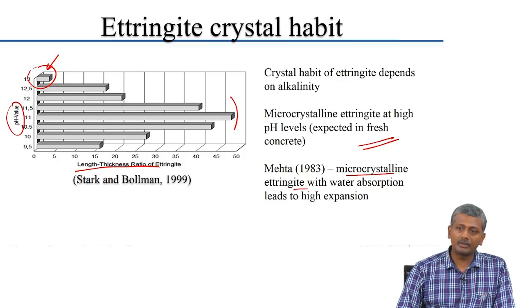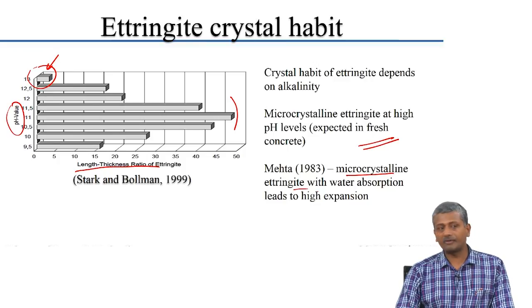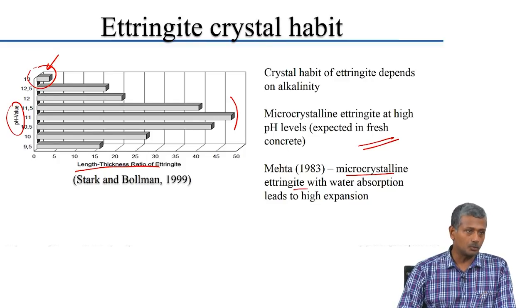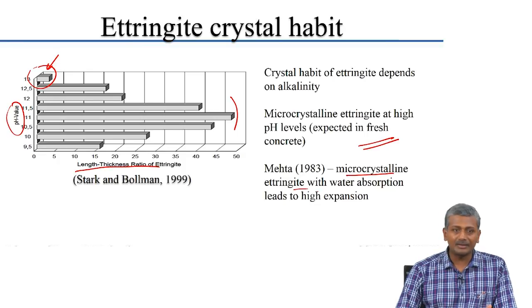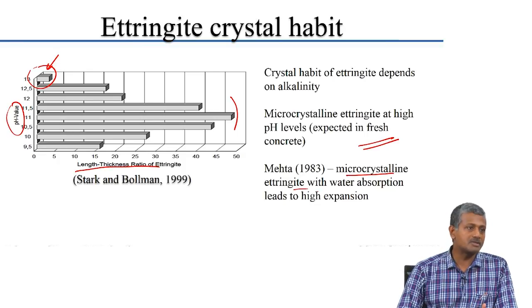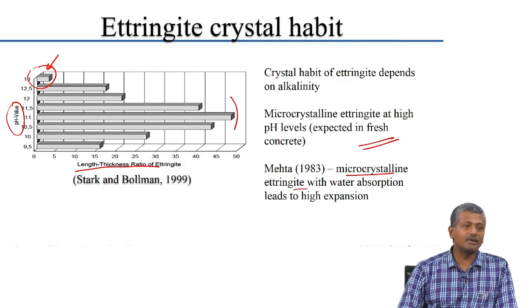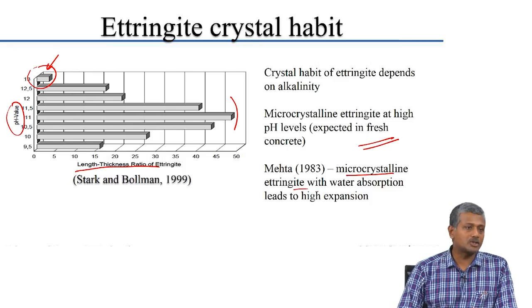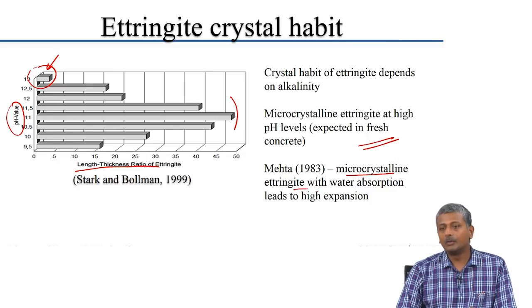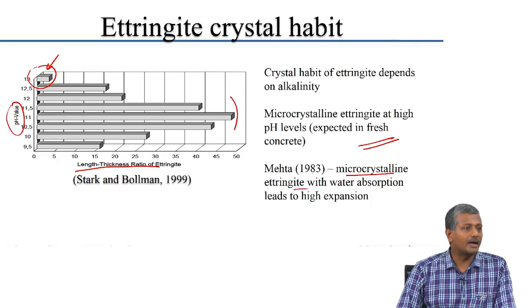When sulphate exposures bring down the pH — for example when you have lower pH levels in the surrounding environment — the ettringite that actually forms in the system may not be highly absorptive. When this ettringite does not absorb or imbibe water, it does not lead to very high expansions. So ettringite formation can lead to expansion primarily only in those conditions where the external pH is also high enough.